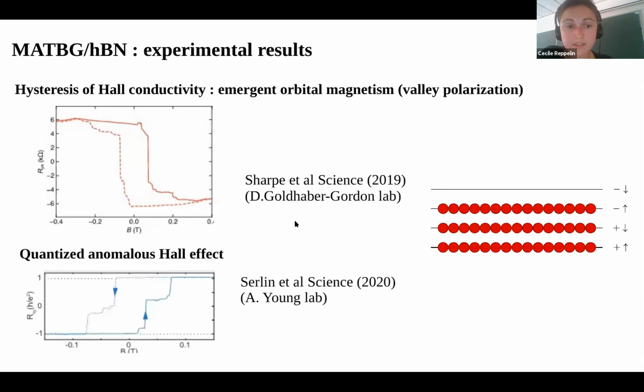And subsequently, a quantized anomalous Hall effect was also found. So note here that in the first experiment, the Hall resistivity is quite large, 6 kilo-ohm, but that's still smaller than the von Klitzing constant, which is about 5 times larger, a little less than that. So subsequently, quantized anomalous Hall effect was also observed. So here again, there's a hysteresis of the Hall resistivity.